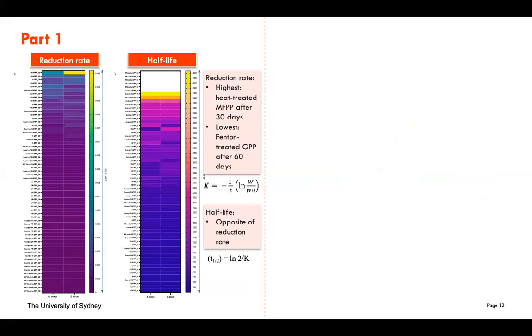Right. And then we also measure the reduction rate. The reduction rate actually measures how much polypropylene has been degraded per day, while half-life determines how long it takes to fully degrade half of polypropylene samples. So you can see the formula for reduction rate here. It is divided by time. So we calculate for every 30, 60, and 90 days. We can see that the highest reduction rates are observed for the metallized film after 30 days. Because you see that although the weight loss increases from 30, 60, and 90 days, the highest reduction rate, of course, will be occupied by the 30 days because we divide it by time, which is the days, right?